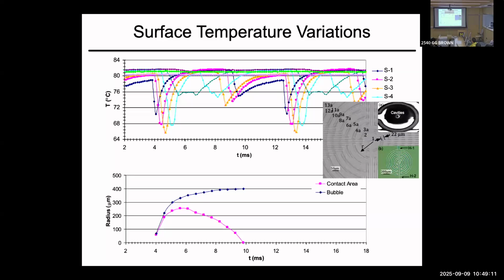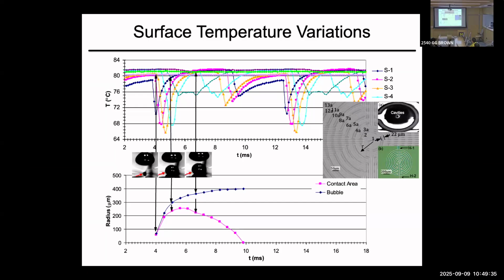In this case, as the bubble grows, it appears on the surface and covers the first layer of sensor, and the temperature very rapidly drops, indicative of rapid cooling at the surface. As the bubble keeps expanding, it covers more and more sensors, sensor 1, 2, 3, 4, and they experience very rapid cooling of the surface. As the bubble expands, the temperature of these sensors recovers, meaning that there is no cooling anymore.